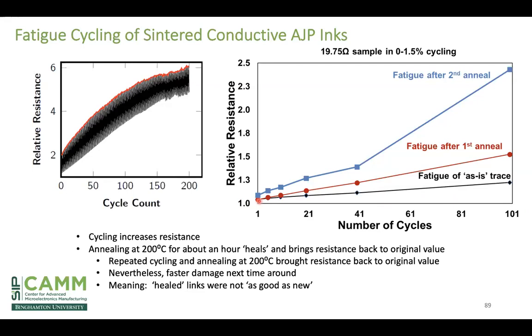resistance. But what we learn through this process of this subtle cyclic fatigue is that, of course, we are causing damage. And damage is accumulating because after the first anneal, yes, we start at the same low resistance at the beginning, but after 100 cycles, we certainly have a higher resistance. And after the next anneal, we do not even start at the same point, but we're at even a much higher resistance. Now, keep in mind, we're talking relative resistance in single digits here.